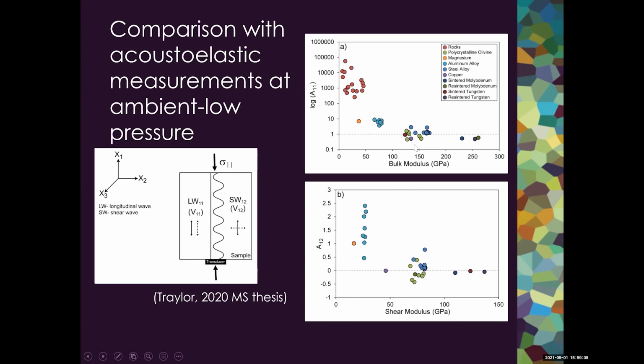And we can see that our samples of polycrystalline olivine are plotting in the range of other metallic material studies that were performed at lower pressures. So we have some steel alloys and copper and tungsten. Similarly, when we plot the shear wave acoustoelastic constant as a function of the shear modulus, we observe a decrease in the A12 acoustoelastic constant with shear modulus increase. And again, our polycrystalline olivine samples are plotting within the range of other metallic materials.